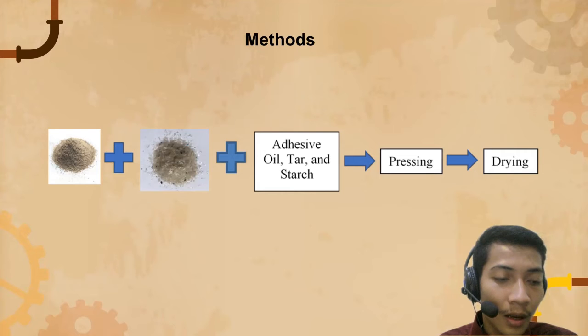After all ingredients were ready, rice husks, plastic waste, and the adhesive were mixed with a composition ratio of 70%, 30%, and 100%. Then the 1-inch diameter cylindrical briquettes were molded using a compaction system with a pressure of approximately 120 kg per square centimeter. After molding, drying was done for 3 days, 1 day at room temperature and 2 days under the sun. Based on the samples, the average weight of the briquettes was 16 grams. The briquette testing was carried out at the Forest Product Technology Laboratory, Faculty of Forestry, Universitas Gadjah Mada.